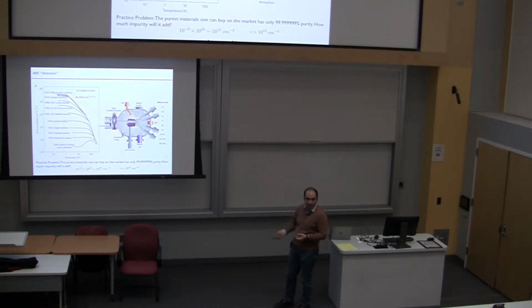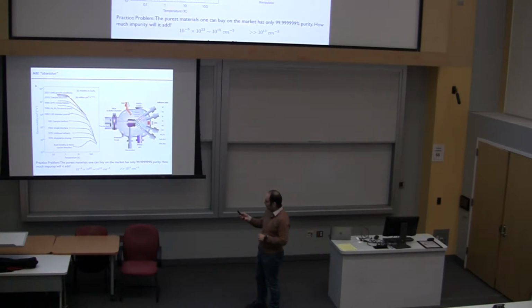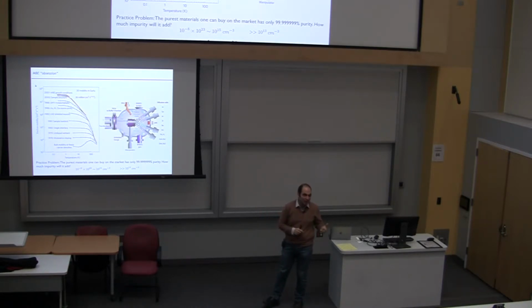But luckily the best thing that we can do is 10 to the 13 background impurity, and that can be achieved in the growth of gallium arsenide. If you do the exact same thing with the best chamber and try to grow indium arsenide, this number 10 to the 13 goes up to 10 to the 16. It's just because now you are choosing different materials, and the impurity levels inside the materials are different. It's a very subtle game where for each material you have to be focused. Unlike bulk growth, people are usually stuck with what they set up the chambers to do. You cannot move too much.